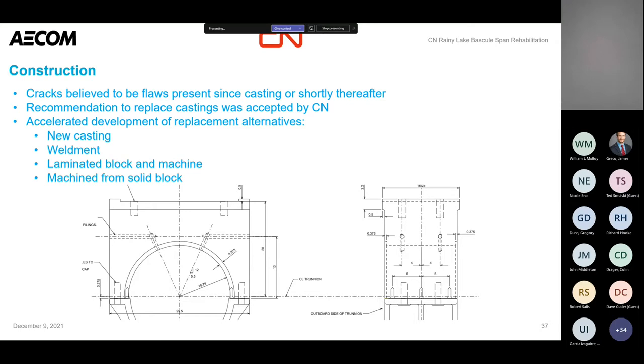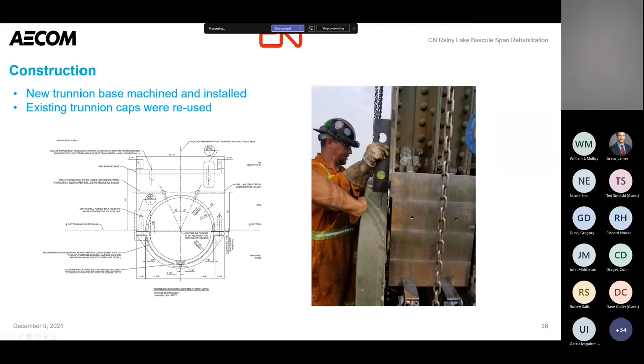This is what we ended up with. We quickly developed drawings for the new element — essentially a big block of steel machined to receive the new bronze bushings, with holes for grease to get into the bushing itself. The cap we actually maintained: although it did have some cracking, the cap sees no load — it's really just there to keep dirt and weather off the sleeve. So we machined the face to receive the new bronze bushing and reused the cap itself.